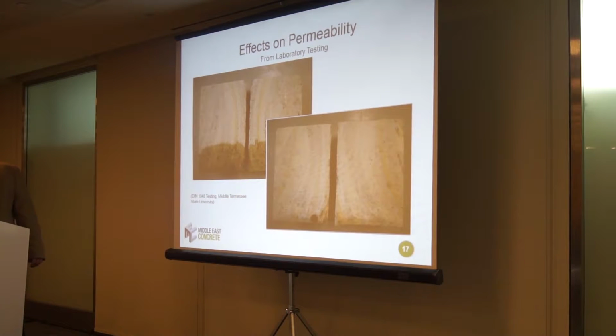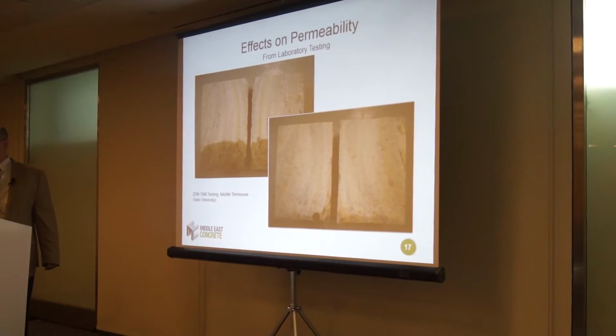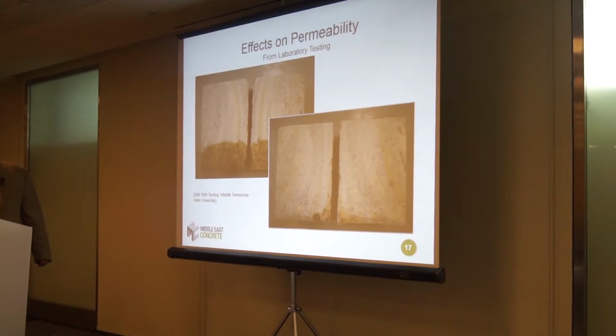Here's a slide from a DIN 1048 test. I did say that we did a lot of ponding tests on permeability, but we also ran some DIN 1048, which is a European standard. This sample here was a particularly bad concrete with a water cement ratio of up around 0.60 or so.